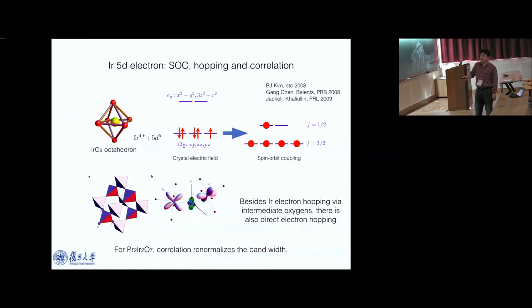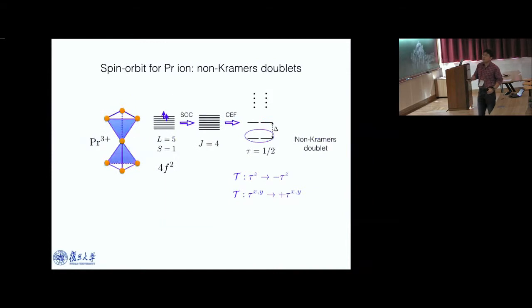You can build up some tight binding model. Although the correlation would renormalize the bandwidth, you can still build up a tight binding model because this material is always metallic. You can build up a tight binding model with a renormalized hopping parameter from the very beginning. So then you can capture the correlation physics from the very beginning, right? But at the same time still preserve this correlated band touching in a certain parameter regime. So this is the local moment physics.